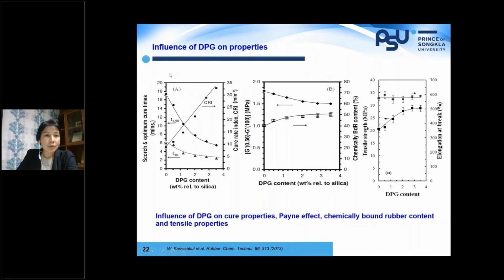Let me show you the influence of DPG on properties. As I mentioned, this is an important ingredient for silica compounds. There was a report many years ago showing the effect of DPG content on properties. So we can see an enhancement in cure property in the presence of DPG and improvement in the Payne effect. So we can see a lower Payne effect here and higher chemically bound rubber when we increase the DPG content, and we can see a clear improvement in tensile property.